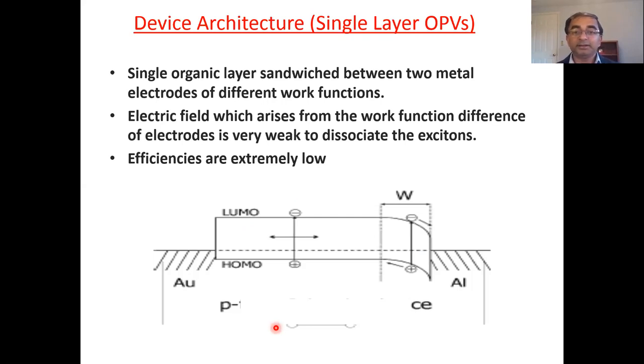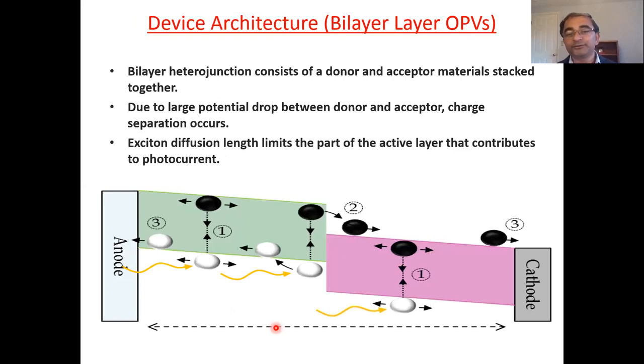So what they have done, they again take the architecture from the PN junction silicon solar cell. So one side is a donor, and another side is the acceptor material, P and N. And even then the efficiency is very less, because it all depends upon the diffusion length of the exciton also. At the edge, it is dissociated, but in the bulk of the material, they recombine, because the diffusion length should be greater than L, only then will you get a good collection efficiency and higher efficiency of the cells. But again, this is a problem, because the diffusion length is not up to the mark to collect all the electron hole pairs which are generated at this junction at the electrode.